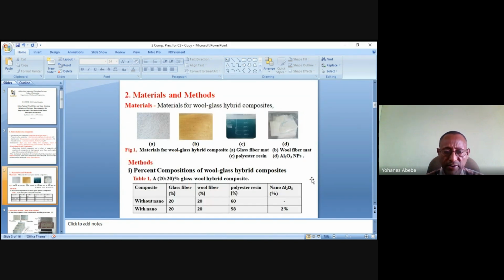When we look at the materials and methods, the materials used to produce the composites include wool fiber, glass fiber, polyester resin, and nano-alumina. The method I employed to manufacture the composite can be seen in table 1, the percent composition of wool to glass ratio for hybridization. Equal volume, 20%, is used for production of the composite. One set of the composite is with the application of nano, 2%, and the second set is without the addition